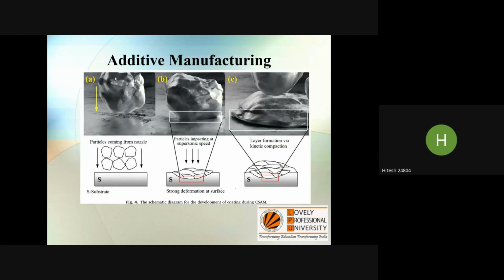So the powder particles are coming out of the nozzle, which you can see in this first one, and striking on the substrate material where you want to deposit this powder material. And in the second part here, the velocity is very high. In the cold spray technique, the velocity is maximum as compared to the other processes. So that is why the supersonic speed is mentioned here: the particles impact the surface at supersonic speed.